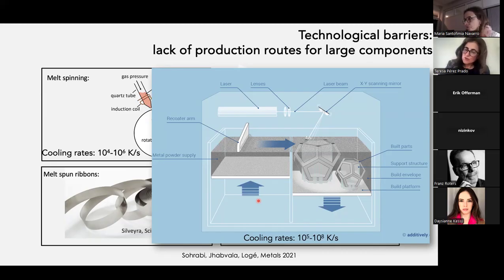A window of opportunity opened when additive manufacturing techniques became more widely available a few years ago. The technique I'm going to focus on in this talk is laser powder bed fusion. For sure, many of you already know how it works, but I'm going to highlight two important characteristics of this technology that are very relevant for what we are talking about today. One is that, as you know, this is a layer by layer process. As the laser melts this specific powder layer, the material locally cools down very fast, at rates between 10 to the 5 and 10 to the 8 Kelvin per second. This covers the range of cooling rates that we need to stabilize the amorphous phase in the metallic glasses that we are studying today.